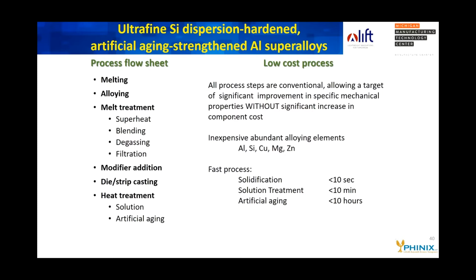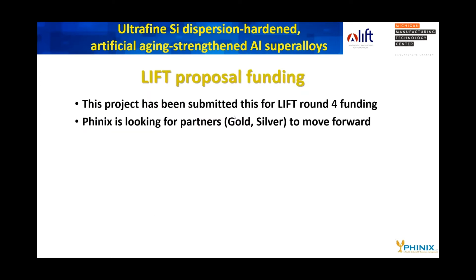The process is fast. The solidification takes less than 10 seconds. Solution treatment, less than 10 minutes. And artificial aging, less than 10 hours. So that gives us the potential for a very low cost process, for a material that can be recycled back into A390 alloy, and that can be batched from recycled materials.